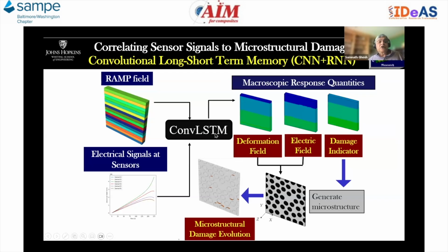First we tried this ConvLSTM, where the electrical signals at the sensors together with the ramp field are inputs to this convolutional long short-term memory network, which combines convolutional neural networks and recurrent neural networks. From here you get the deformation field, the electrical field, and the damage indicators in the entire domain. This is the full field representation of the macroscopic responses. Once we know that, we can identify the hotspots, and from there we can solve the micromechanical problem to get the microstructural damage evolution.